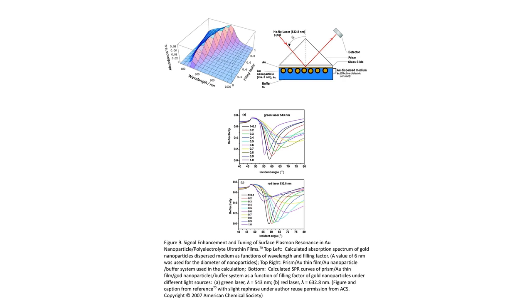They found that the system showed pH sensitivity, with the plasmonic hotspots between the nanoparticles being dependent on the distance between them, which could be controlled by the swelling of the polymer. Their computational models, based on Maxwell-Garnett theory, matched well with the experimental results, showing how the filling factor of nanoparticles in the film could be used to tune the SPR response at different laser wavelengths.